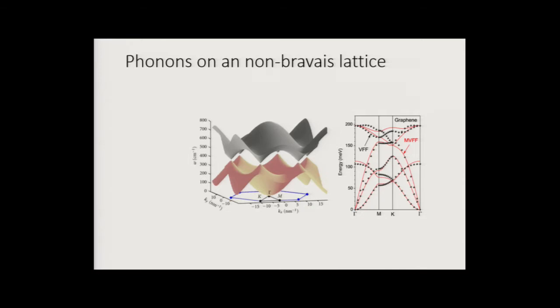So it's a very interesting example if you look at the non-Bravais lattice and you look at the phonon spectra, you have a Dirac crossing point. And like I said, I never paid attention to the phonon behavior. But this crossing point here is very similar to the Dirac point in graphene, right? For the phonons, you have two sites per unit cell. Each of the atoms has 3 degrees of freedom, so you have to have 6 branches. So it's a much busier band structure for the phonons.